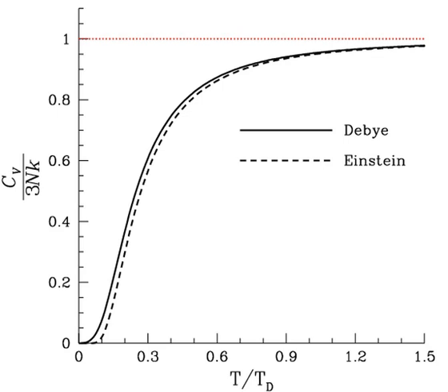Since the volume-specific corollary of the Dulong-Petit specific heat capacity relationship requires that atoms of all elements take up, on average, the same volume in solids, there are many departures from it, with most of these due to variations in atomic size. For instance, arsenic, which is only 14.5% less dense than antimony, has nearly 59% more specific heat capacity on a mass basis. In other words, even though an ingot of arsenic is only about 17% larger than an antimony one of the same mass, it absorbs about 59% more heat for a given temperature rise. The heat capacity ratios of the two substances closely follow the ratios of their molar volumes, the ratios of numbers of atoms in the same volume of each substance.